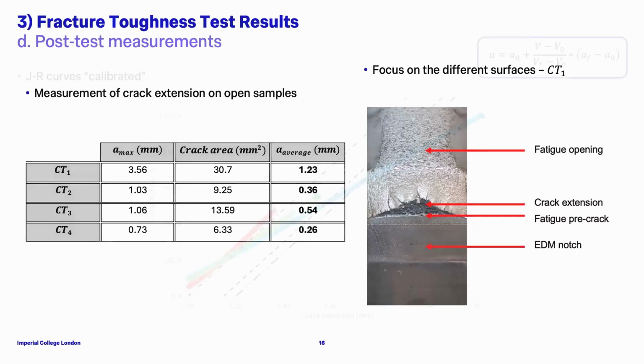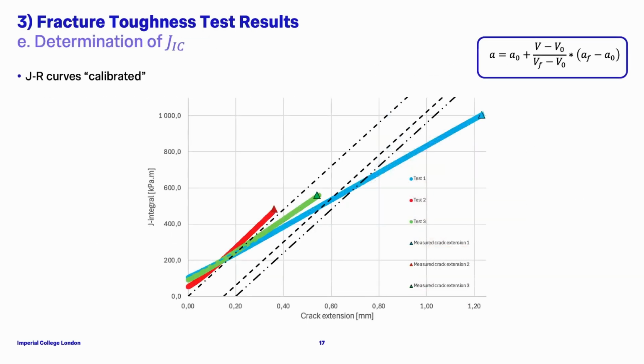So what I did is, instead of using the shape function that I mentioned, I used this expression relating the voltage to the crack length, where af, my final crack length, and a0, my initial crack length, are the ones physically measured. So I could replot my first three JR curves, and the results are much different. For instance, the first test gives a JIC value around 600 kilopascal meter, and for the red curve it is almost infinite. I don't know when it will cross the 0.2 line.